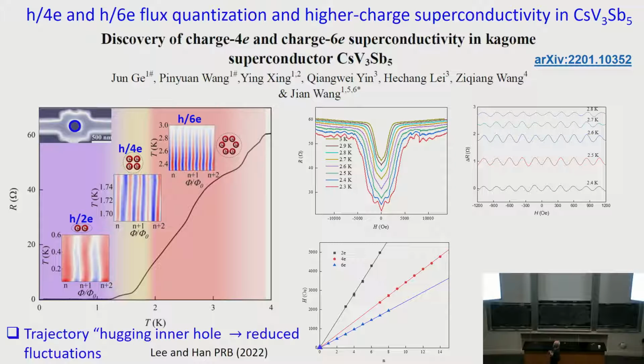So then we were debating, and then Patrick Lee and Junhong Han wrote a paper. They say if you have such strong fluctuations, then they did a time-dependent Ginzburg-Landau calculation and showed the actual trajectory is hugging the inner hole, because once you come so close to the wall, you can't fluctuate into the hole, right? Because there's no material there. That reduces the fluctuation, and that should be the case. But that wasn't good enough to convince the referee.